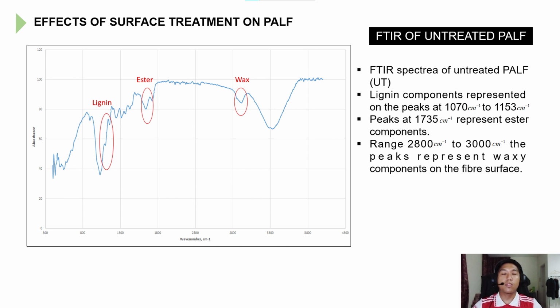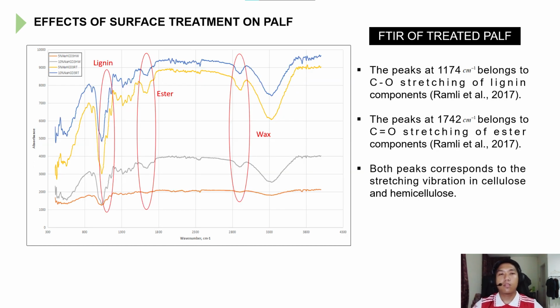Next, we have the effect of surface treatment on pineapple leaf fiber. This is the FTIR result for the untreated fiber. As you can see, I have highlighted regions where there is lignin, ester, and wax. So these are the FTIR micrographs of the treated fibers. For the lignin, ester, and wax regions, you can see there is a reduction of intensity of the peaks. So this shows that the alkaline treatment is effective in removing these components.